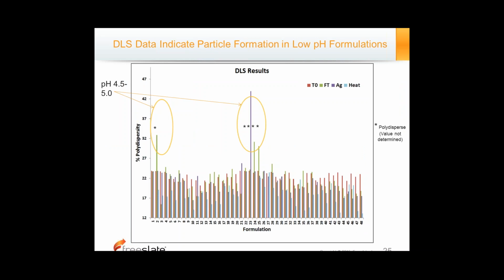In this particular case, I wanted to just highlight some of the DLS data. For this particular study, we noted that particle formation was evident in the lower pH formulations. We can see here that we have 4 different points. We have the T0, so the unstressed material in red. In green, we have the freeze thaw, which was done off the deck. But the agitation in purple and the cyan data, which is heat treated, those latter 2 were actually stressed on the system, on the BFS system, in parallel, and then we analyzed those materials with the DLS.